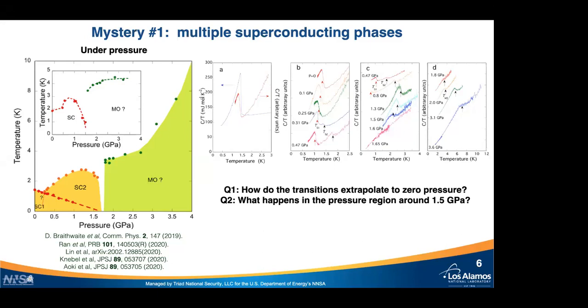When we saw some of these results, many questions started to arise. The first one is, how do these transitions extrapolate to zero pressure? That's an important question because we want to know whether there are two transitions in this material. This will help us understand what the order parameter is. And the second question is, what really is happening in this pressure region around 1.5 GPa?